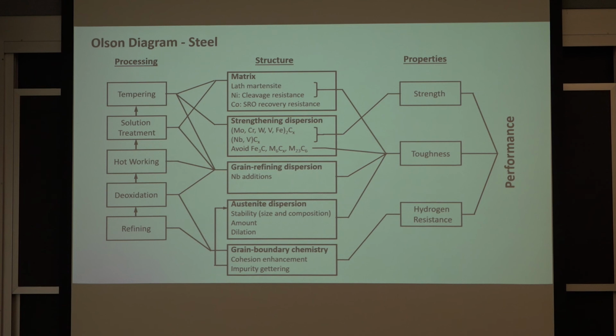So again, you've designed in a secondary strengthening mechanism. You've reduced the grain size for whatever's left, whatever didn't turn to martensite—for example, austenite. And then there's another topic: you can design the alloy so that when you quench it, you retain some of that austenite. It doesn't all transform to martensite.